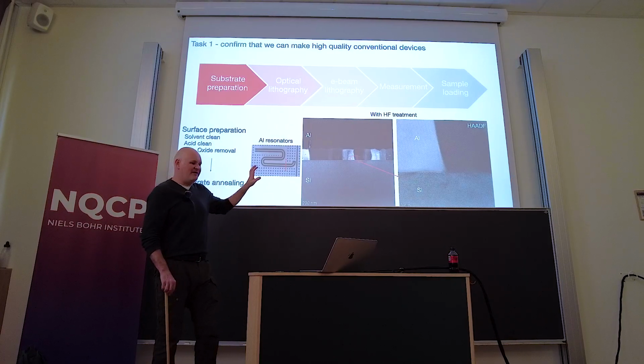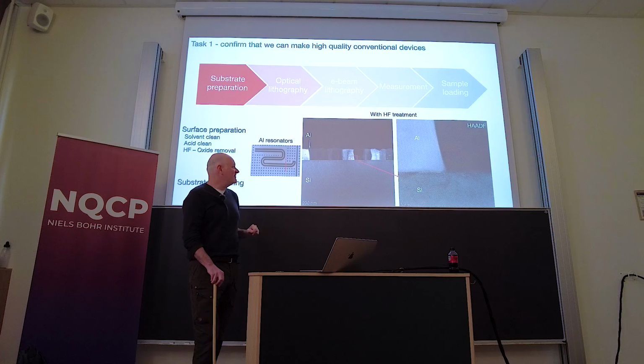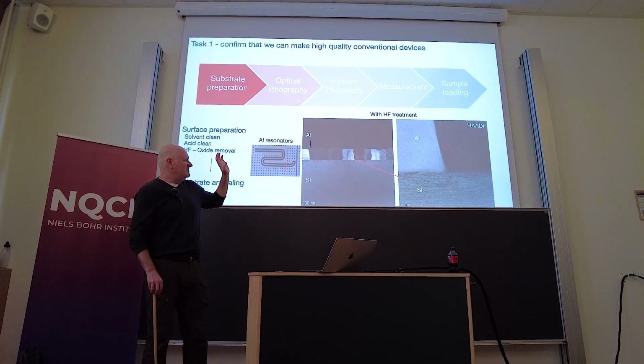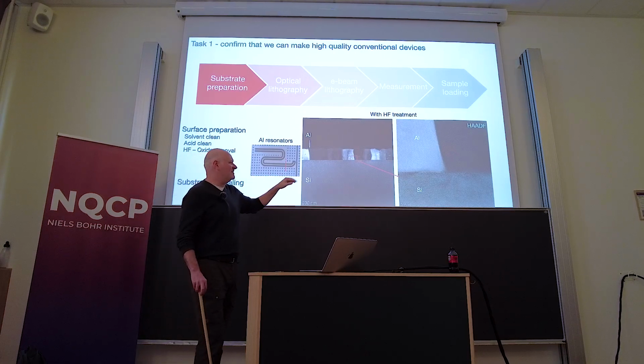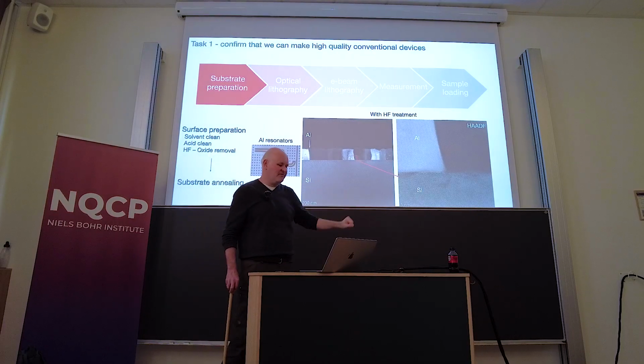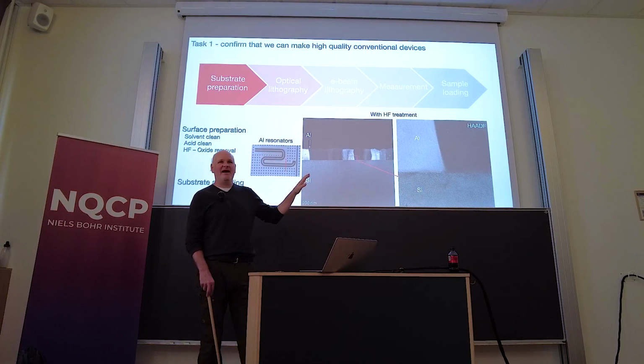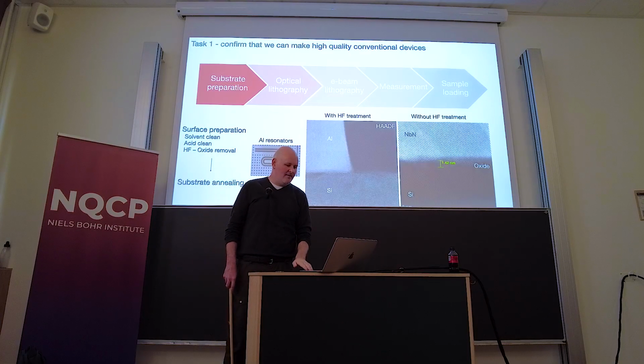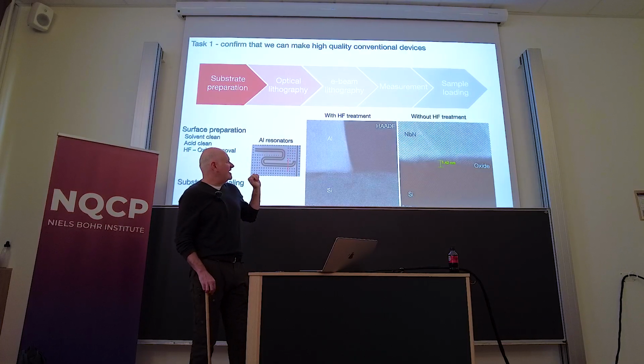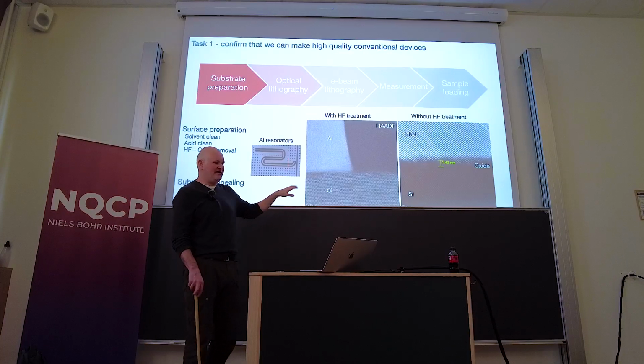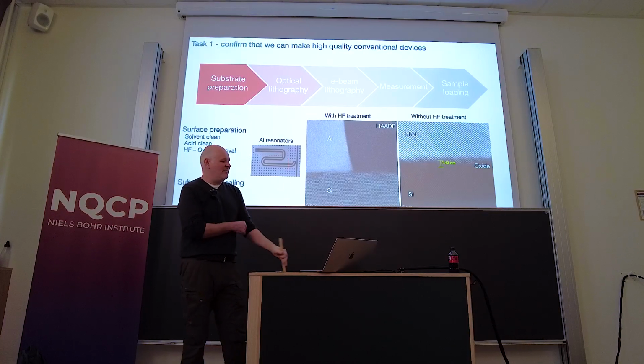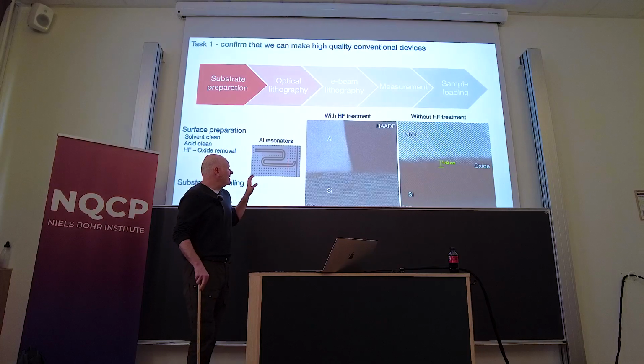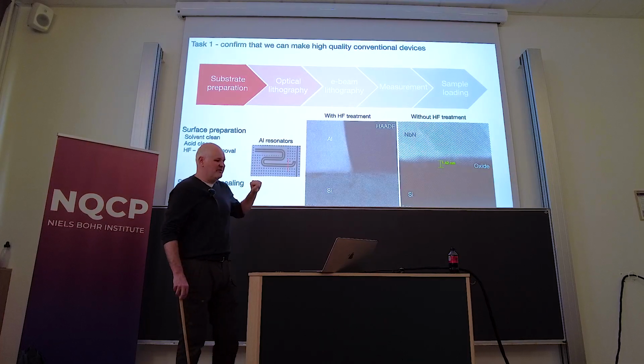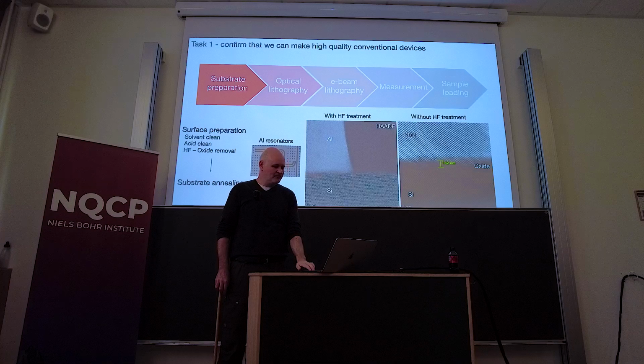So I think a lot of these slides will be very familiar to many of you, but essentially we just did very careful surface preparation, did aluminum deposition, and then did high resolution microscopy so that we could see that we indeed did not have oxides at the interface. In the case of not using HF treatment, we could very clearly see that there was always a silicon oxide, which again you would expect, but it is nice that you can see it. And these measurements are all done on actual aluminum resonators, so after fabrication.